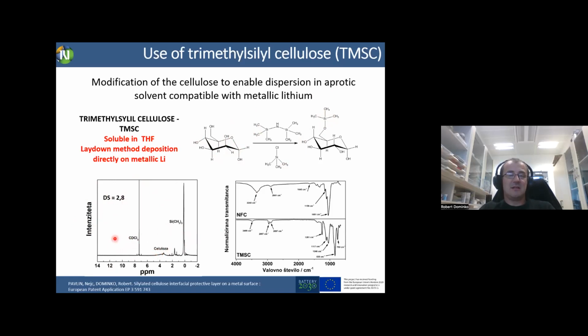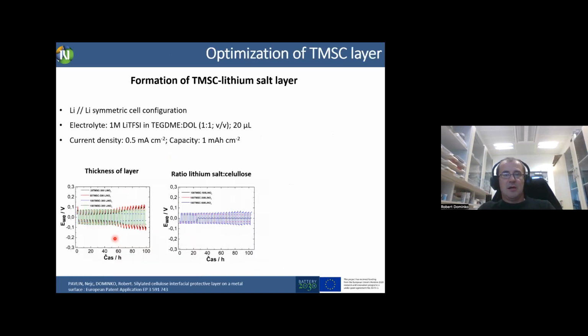and we can create more or less completely silylated cellulose. That's one of the derivatives which we are using, but we are also developing some other derivatives which can be adapted even to shift from liquid electrolyte to polymer electrolyte and the so-called all-solid-state configuration. Anyway, this silylated cellulose, if I can call it in short, gives much better results, but still keeps some kind of porosity inside. And if you fill that porosity with electrolyte, then the electrolyte has direct contact with the metallic lithium, and that creates a problem.